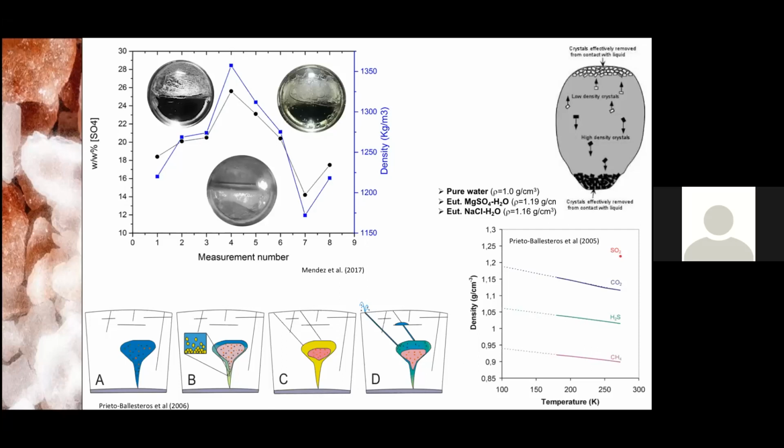So we demonstrate with this experiment the fluid density variation change, measuring by Raman spectroscopy this variation in sulfate concentration during the cooling and heating experiment.